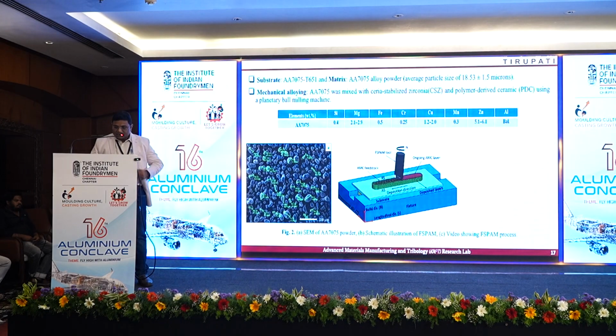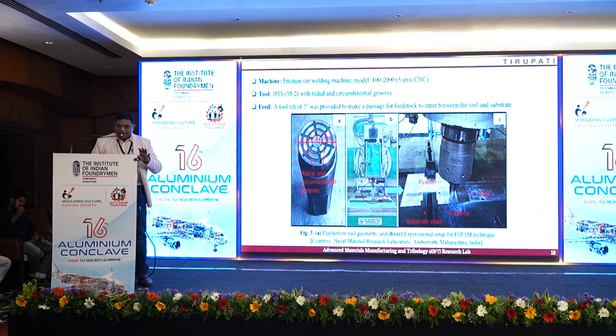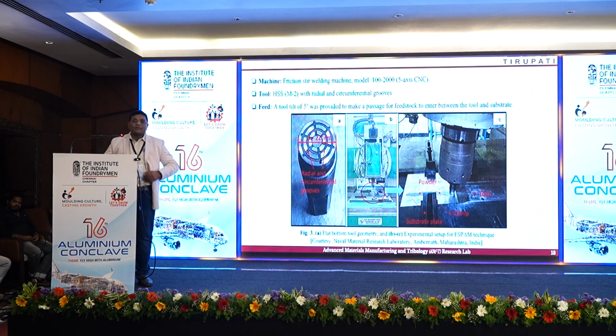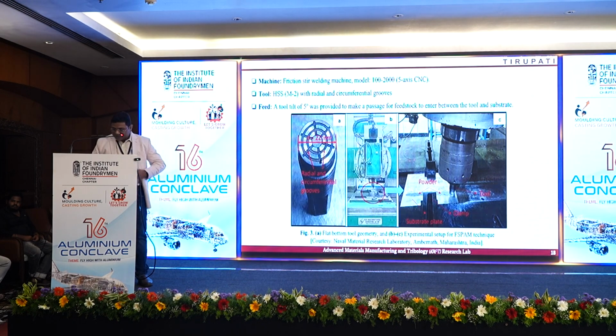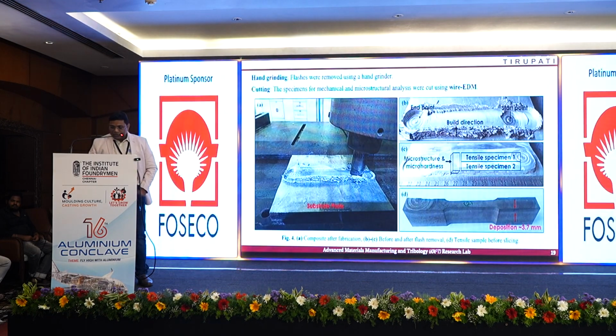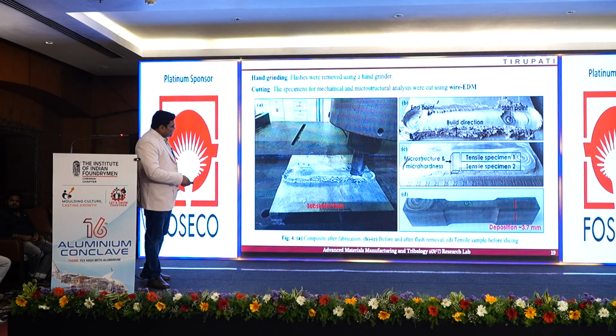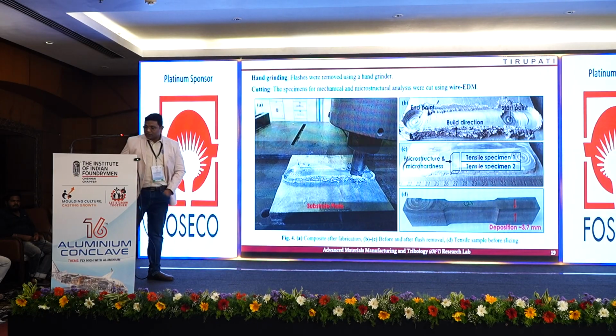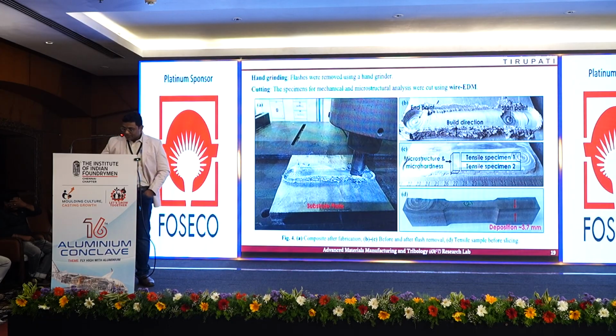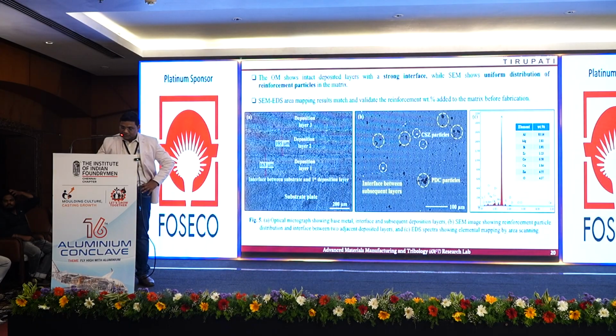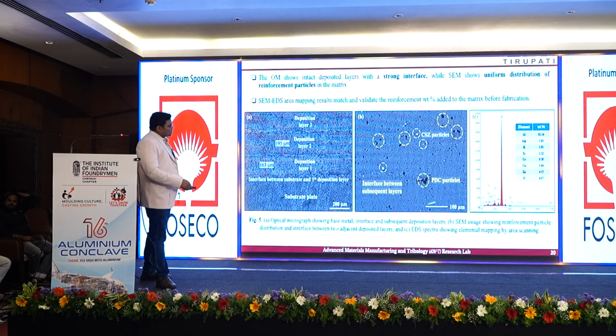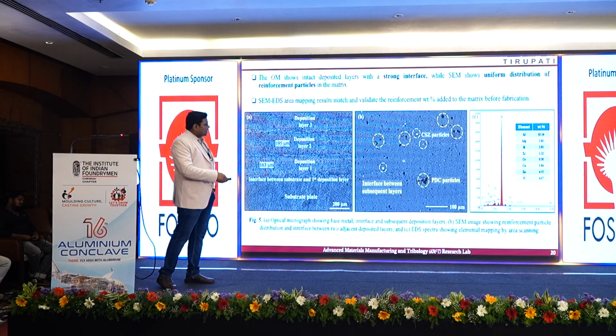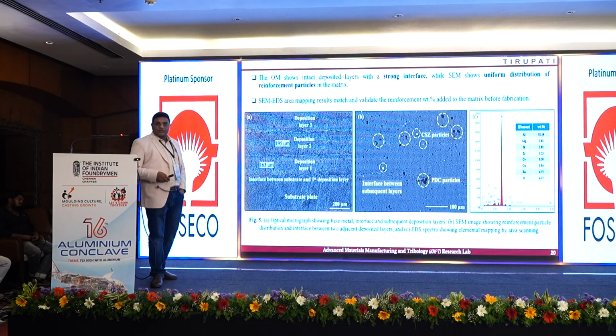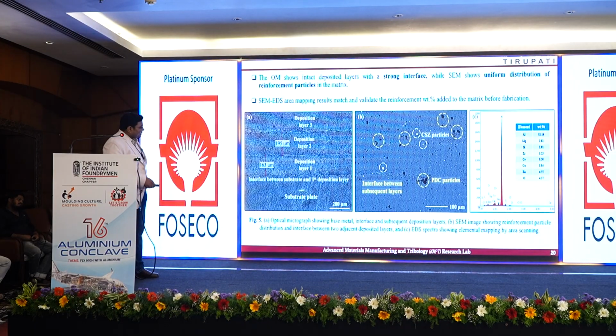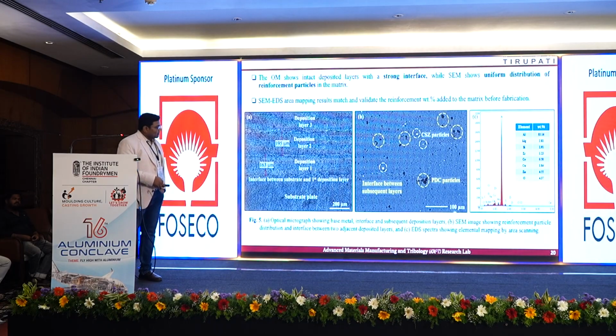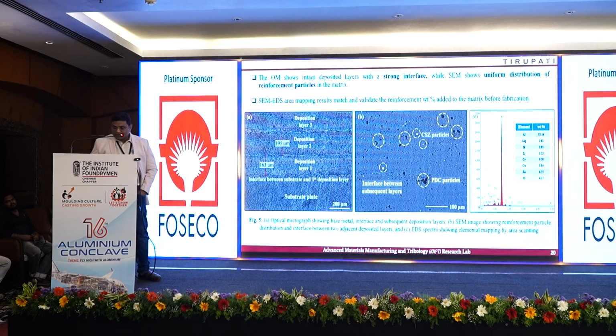We used these materials for the experiments, and we did the experiments on our friction stir welding machine in the lab to understand the physics behind this experiment. We could actually deposit these composite layers, almost 3.7 to 4 mm thickness of composite material. You can see the distribution of the second phase particles inside the matrix. There is no defect compared to the casting, and you can deposit layer by layer. This study we have done at a scale of 100 micron.